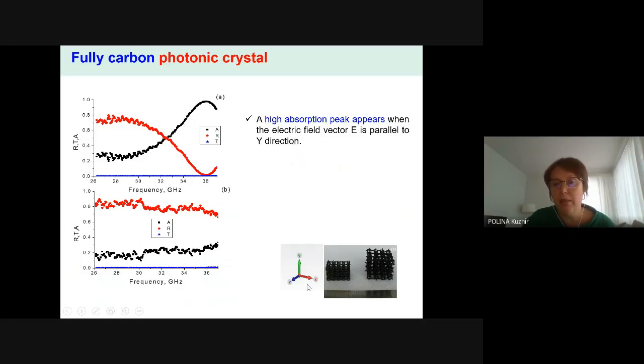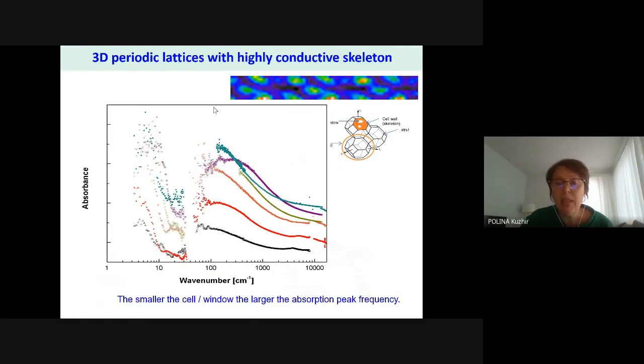We see that when the electromagnetic field is along the x direction, this is an almost fully reflective structure, whereas when the electromagnetic field is parallel to the y direction, at a certain frequency, absorption increases up to almost perfect. This frequency corresponds to the cell size of the structure or to the window size where these cells are connected to each other. The smaller the cell or window, the larger the absorption peak frequency.